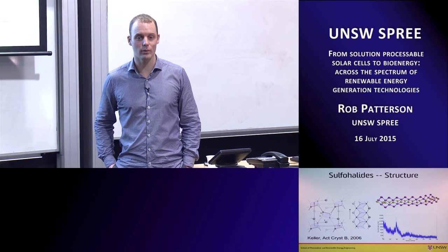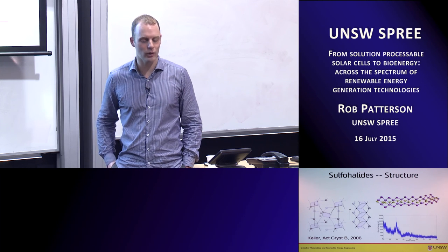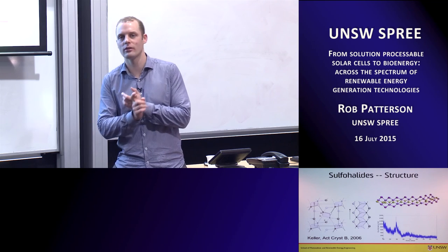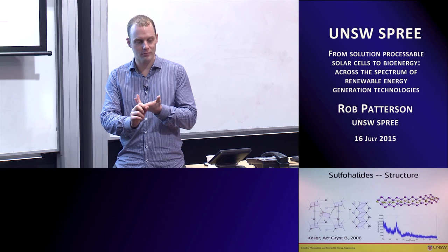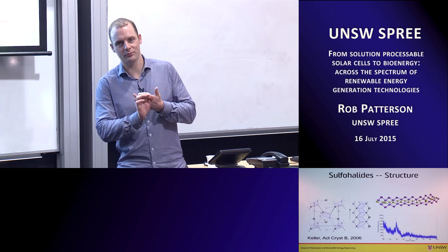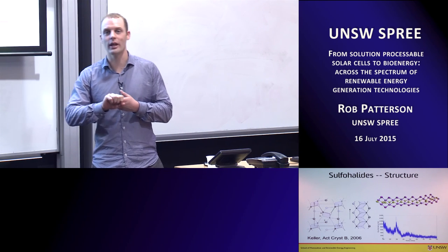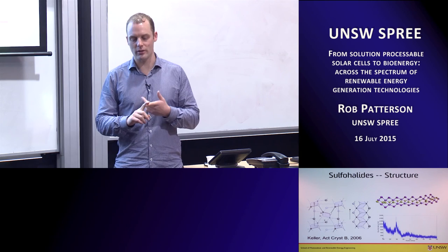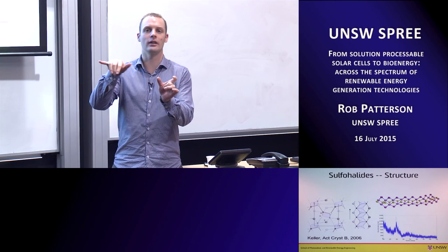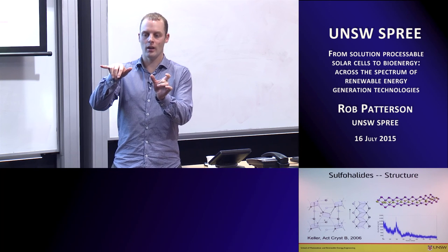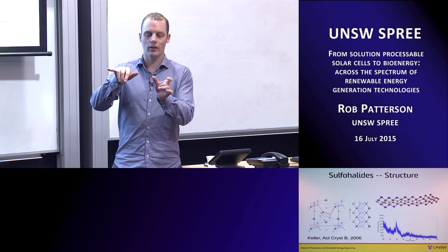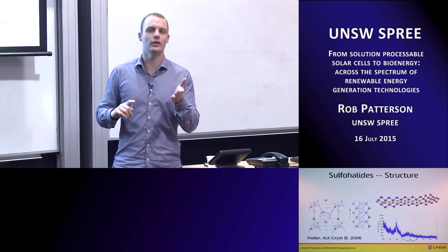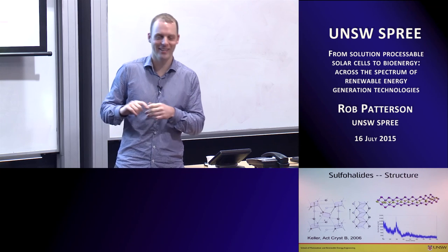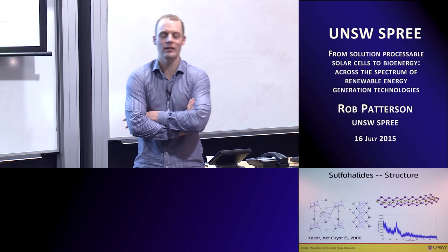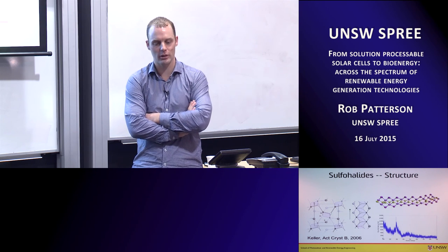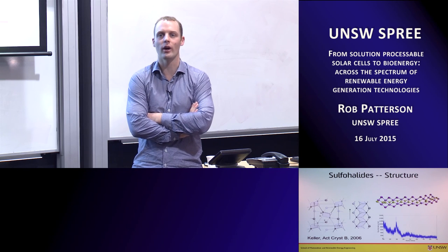It's a very good question as well. When I was doing that, there were three things that I was playing with. One was just electrolytes, basically salt. Ethanolamine, which is not anywhere in this presentation, so I can't show you the structure. But ethanolamine is basically an amine with two carbons and then an alcohol group, an OH group. And so that has the potential to do some soft chelation, yes. It didn't work, as far as I could tell. So it needs a little bit more work. But yes, there are other things that can potentially be tried. This was just the first brute force effort, you're right.